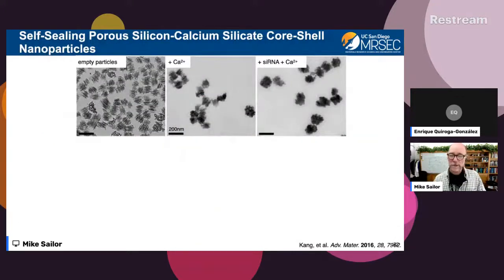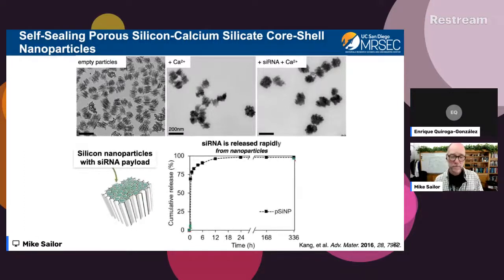And so here's kind of pictures of what these things look like once we've loaded them with nucleic acid. On the left, you see the nanoparticles that are empty, the calcium ion sealing chemistry. You can kind of see how these porous silicon nanostructures get clogged up. The calcium chemistry tends to make them darker, denser. You don't see these nice open pores that you see in the empty particles. And they seem to also include siRNA in them. So we did this chemistry and it worked.